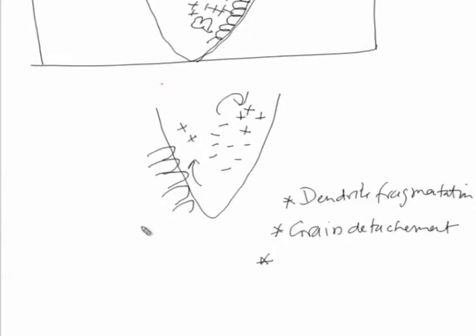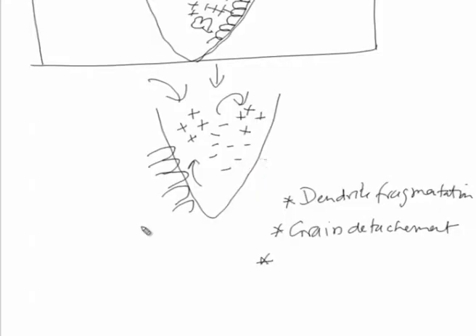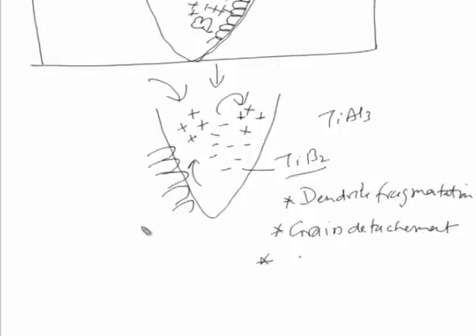The third mechanism is inoculation: we add elements from outside that are able to act as nucleants. Addition of elements from outside which are able to act as nucleants helps in refining the grain structure. For example, addition of TiB₂ in aluminum weld metal or TiAl₃ in aluminum weld metal frequently acts as a nucleant for refining the aluminum weld structure. This approach — adding something from outside — is called heterogeneous nucleation, and it is obtained by adding alloying elements from outside. This is called inoculation.